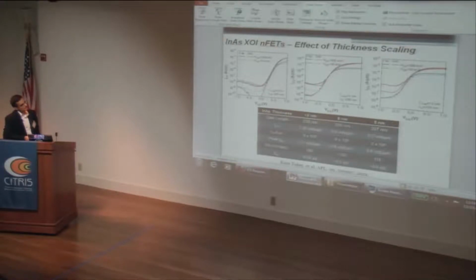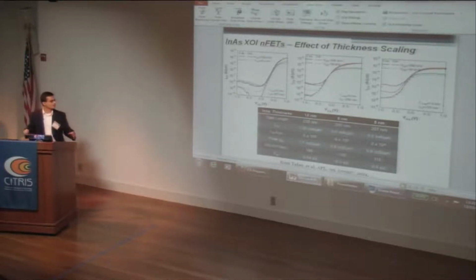And you can see that as you make your devices thinner and thinner, the off current drastically improves, goes from around 10 to the minus 6 to around 10 to the minus 8. And the subthreshold swing also improves from 180 to 125 to 115. And part of this, of course, is because of the electrostatics. The thinner the body, just like SOI, the better the electrostatics. But the other reason, of course, is the band gap. The band gap is also increasing as you make your material thinner. So now you have 2 knobs that are working in your favor for these indium arsenide devices.